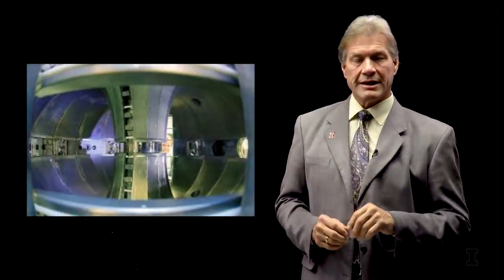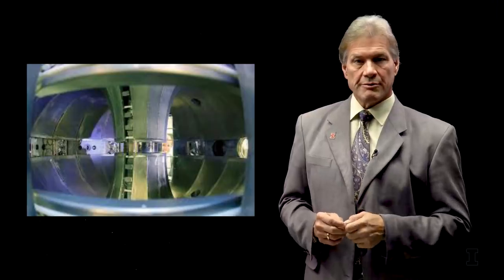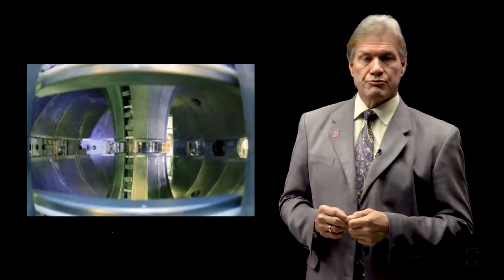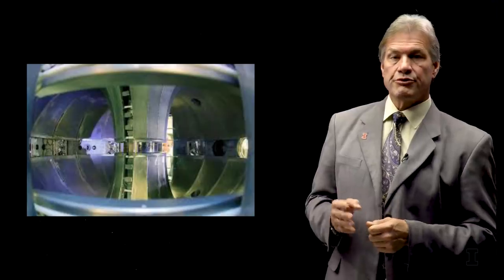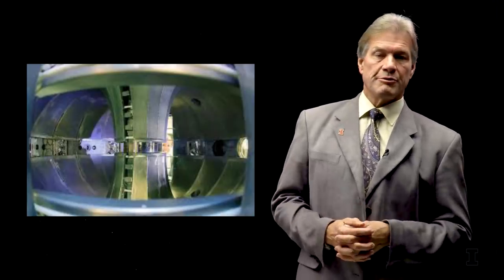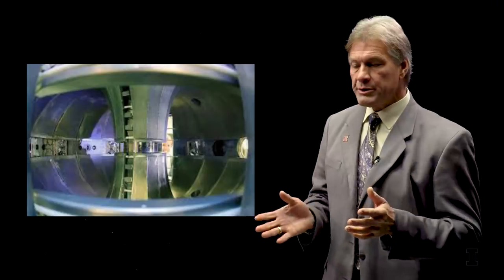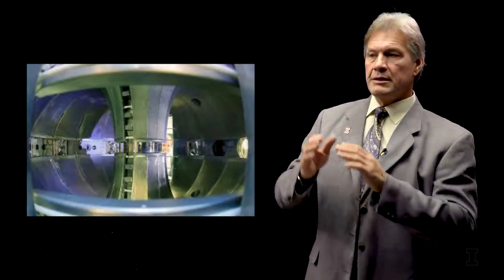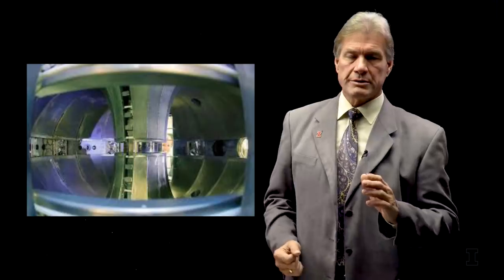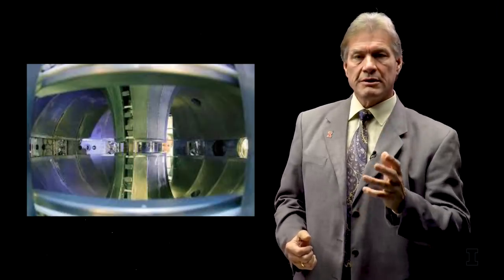Also, people have used this type of lithium concept, not necessarily the TEMHD, but that's all right, in larger fusion devices like EAST in China, and also in a very particular experiment at Princeton that was designed to test exactly this, the Lithium Tokamak Experiment. And what was really fascinating about this is it proved that you get the flat temperature profile. That by lowering the recycling, you actually do get the hot plasma all the way across, and that your confinement goes up.